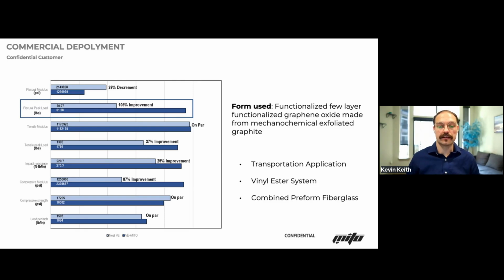And so what we saw is that with this little amount of material, we were able to increase the flex peak load by 105%. That's a massive amount. So to the point that you can do one of two things. You can either take this fiberglass system and use less, a lighter material, use less layers, whatever it may be, or you can officially transition a lot of these other metal systems to this fiberglass system. So because of how we understood how we wanted to deploy materials, what morphologies we really wanted to look at, we were able to deploy something successfully into the transportation market space.